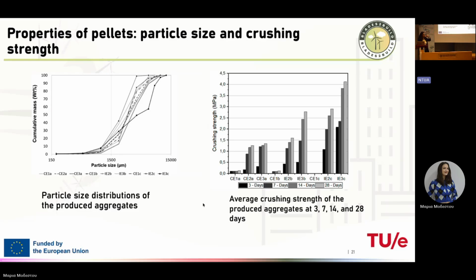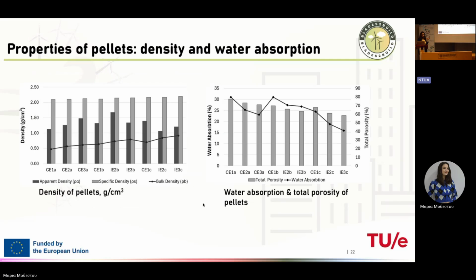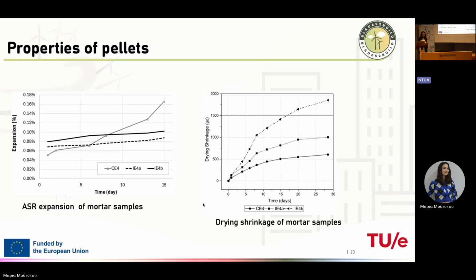The higher the dosage of cement, the higher the crushing strength of these pellets, which is no surprise. And this is the density of pellets. Here is the apparent density, specific density of the pellet, and bulk density. You can see it's more or less the same, but the strength, regardless of the size of waste we used and dosage of cement, is different. And water absorption, and total porosity, was also different. So the more powder we have, the more dense the structure, and the less the water absorption.